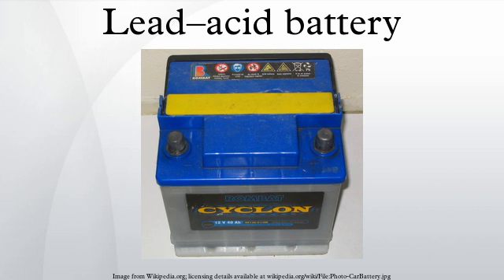Practical cells are not made with pure lead but have small amounts of antimony, tin, calcium or selenium alloyed in the plate material to add strength and simplify manufacture. The alloying element has a great effect on the life and water consumption of the batteries. Antimony alloyed plates provide longer life but calcium alloyed plates are much preferred over antimony for their 8 times lower water consumption. Due to the high price of antimony, nearly all car batteries, valve-regulated sealed batteries, and most other non-industrial batteries have been made with lead-calcium grids since the early 1990s and possibly earlier.